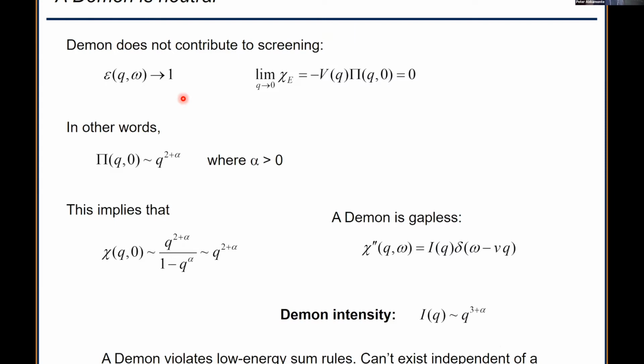Okay, a demon is made of two different charge carriers. The demon mode is where the two submassive carriers flow out of phase. So if I displace the demon coordinate, it doesn't build up any charge on the boundaries, and so the thing stays at zero frequency. That also means that in the long wavelength limit, a demon cannot screen. It can only screen at finite wave vector,